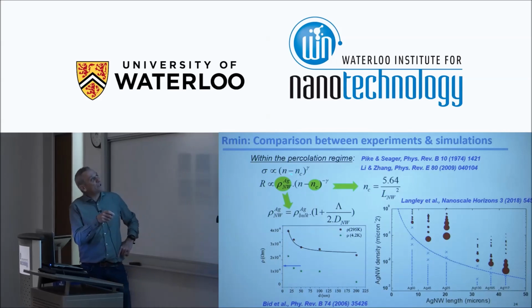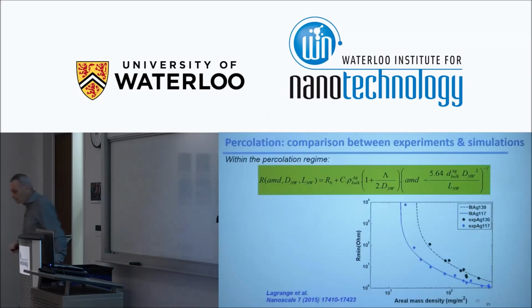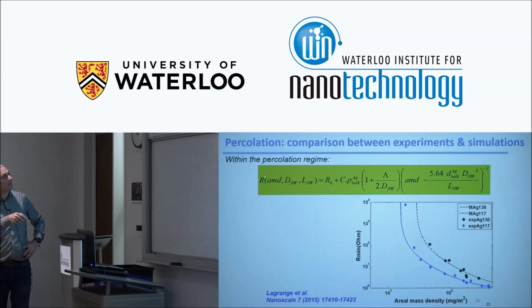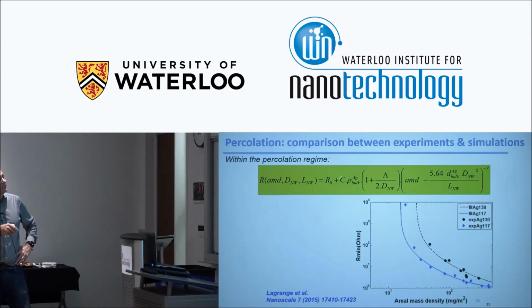So we know that from this. We know this because we know the length, we know the diameter, we know the mean free path. We know nearly everything, so we can put everything together. And for example, calculating the electrical resistance versus the areal mass density of a network, the diameter and the length, average diameter, average length. This is equal to the instrumental series resistance plus C.